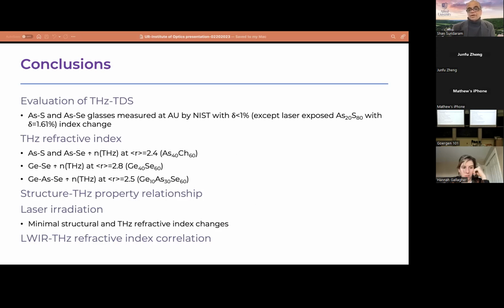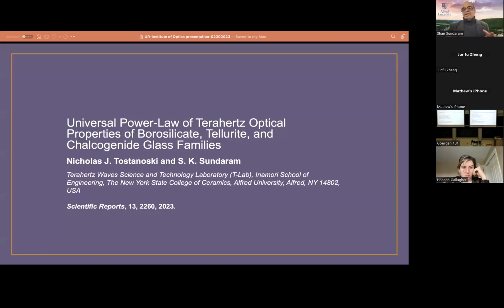Chalcogenide families are also notoriously known for various nonlinear phenomena when you apply ultrafast pulses to them, anywhere from photoabsorption to various processes happening inside, and they also photo-self-anneal even during storage at room temperature, depending on how much light they're exposed to, because of a narrow band gap and a whole range of band gap engineering possible with these materials. So I hope this gives you a little bit broader idea of how a non-oxide glass family can be used for a wide range of applications.